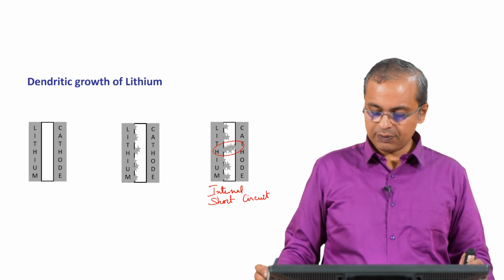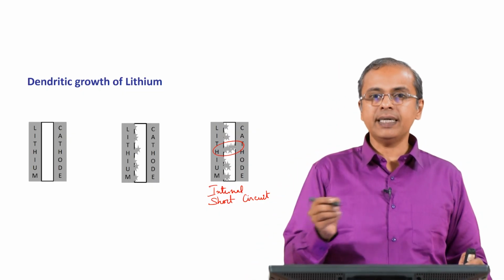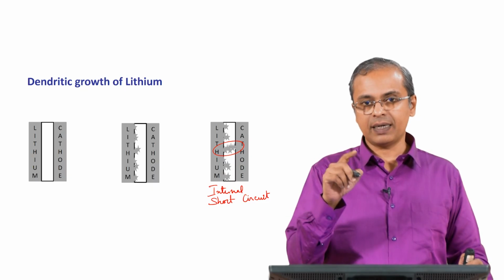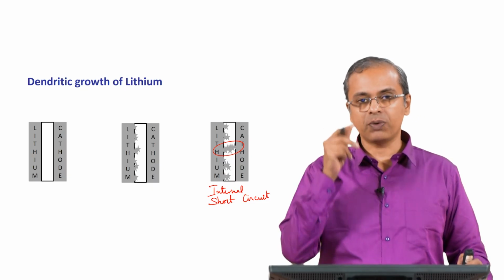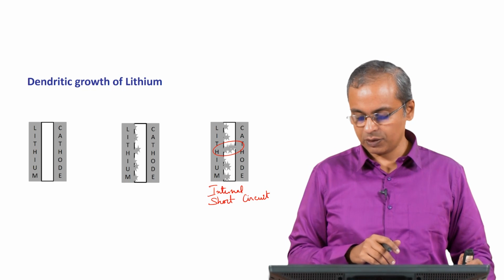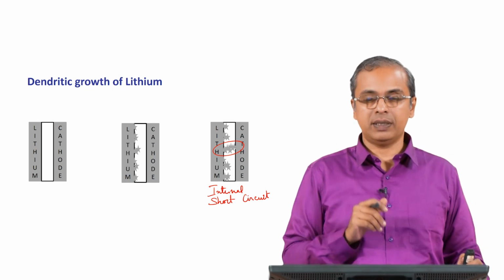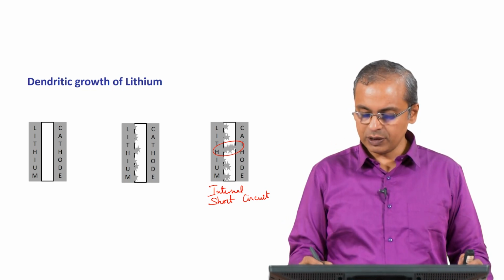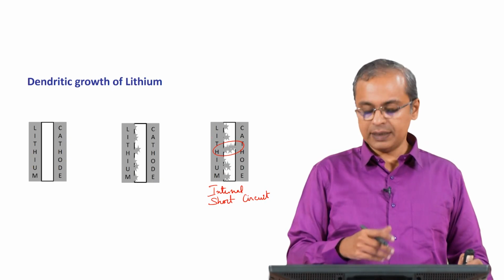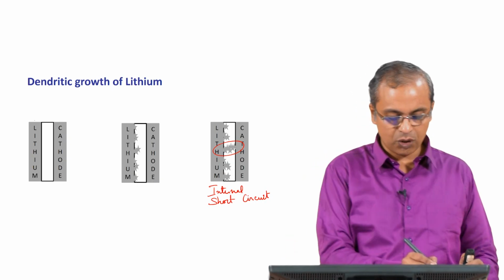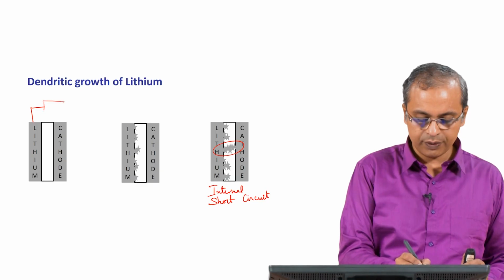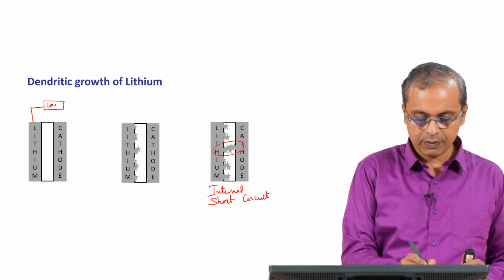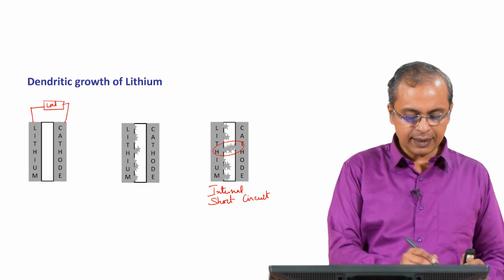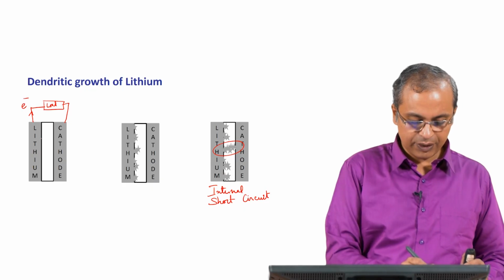Okay. So, what has happened is that with progressive cycling, the lithium metal did not plate flatly, and then it kept growing indefinitely and makes an internal short circuit. This is a very dangerous situation. It is a very dangerous situation because normally you only have to connect an external circuit. Normally we connect an external circuit, we put a load and the electron travels like this and the ion travels like this.